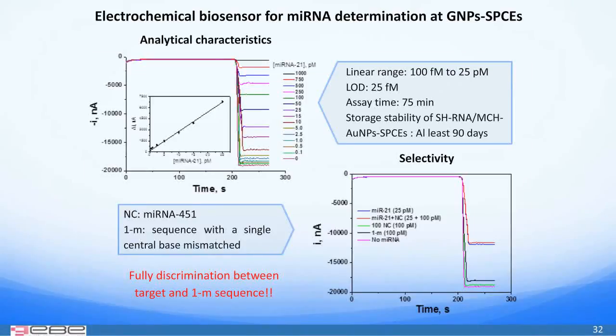Under the optimized working conditions, these scaffolds demonstrate a storage stability of 3 months, a limit of detection of 25 femtomolar, and a linear dependence from 100 femtomolar to 25 picomolar between the diminution of the current value, compared with the current achieved in the absence of target microRNA, and the target microRNA concentration. The selectivity evaluation demonstrates a complete discrimination between the fully matched and the single base mismatch sequence.